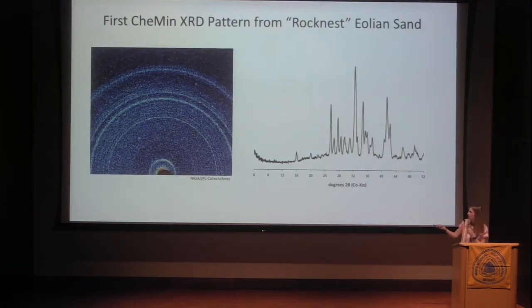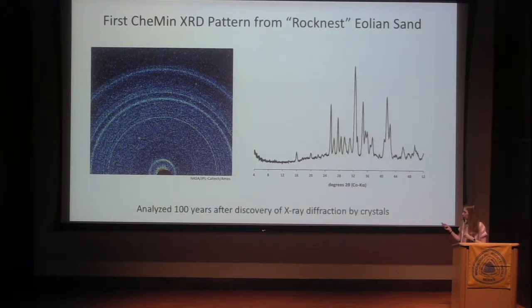And this on the left is our first CheMin two-dimensional X-ray diffraction pattern from a sample that we called Rocknest. It's from an Aeolian sand, and then this is its 1D X-ray diffraction pattern. And just like Doug said earlier, since we're reflecting on the last 100 years, it's really fitting that we collected this pattern exactly 100 years after the discovery of X-ray diffraction by crystals.